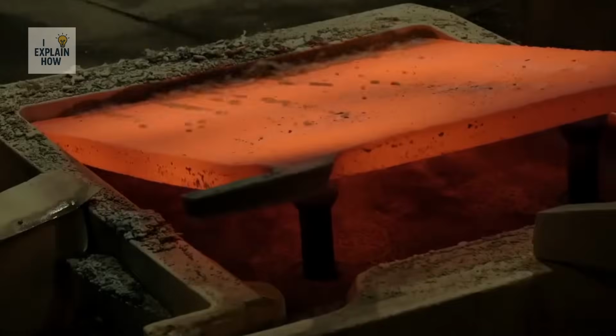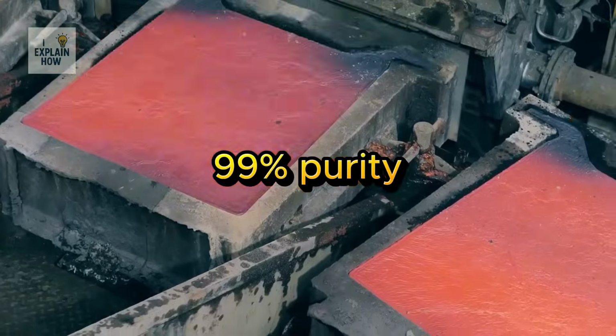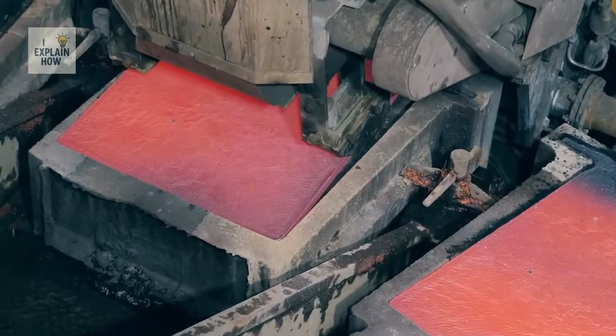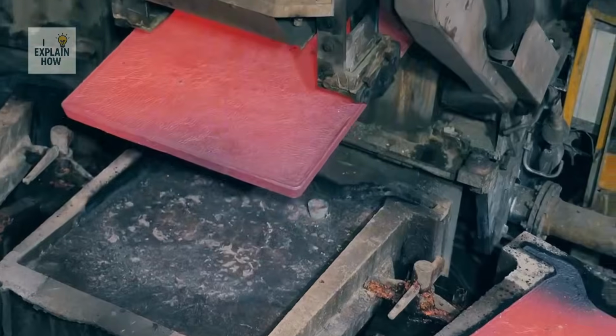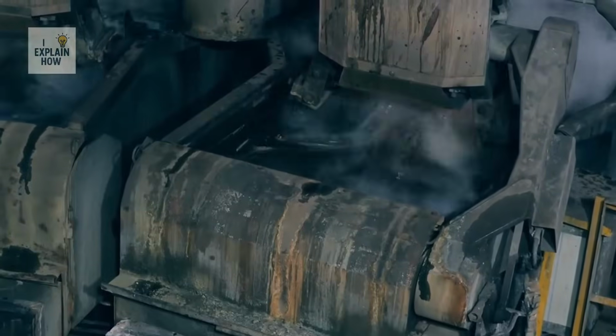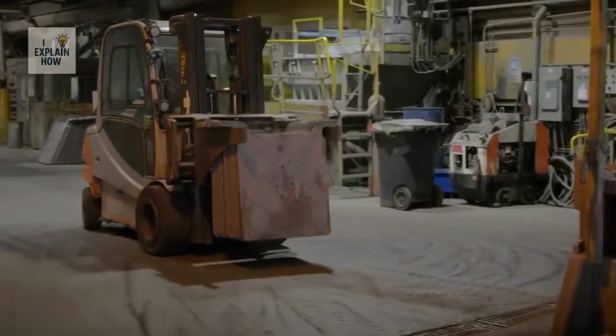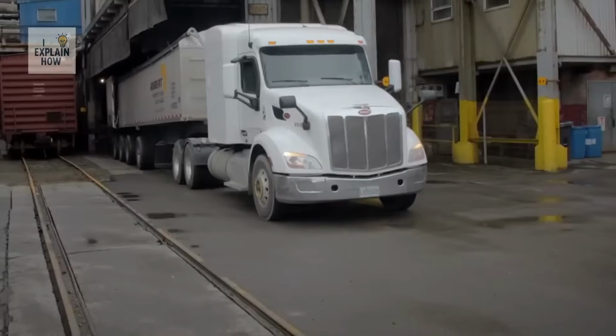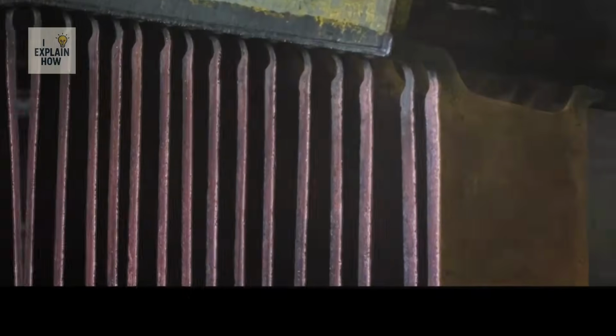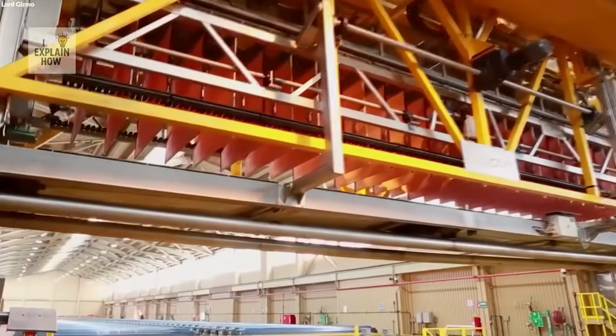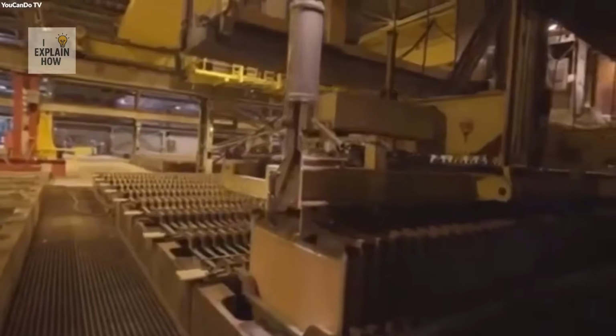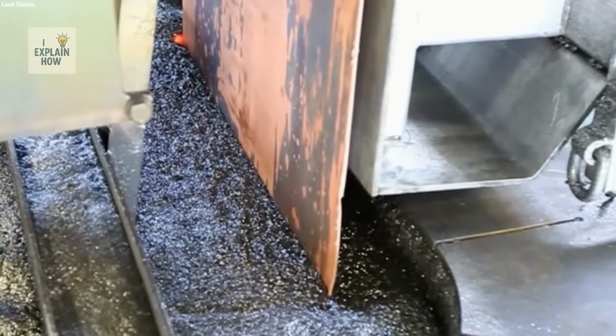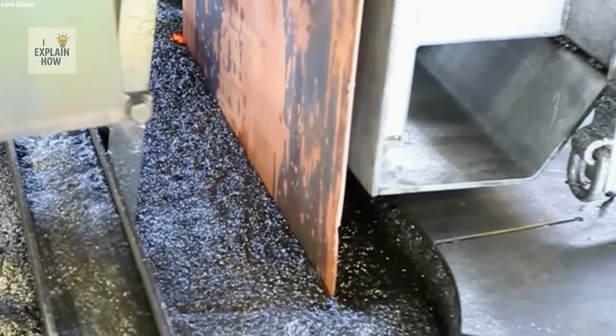The purity then rises to 99%, and the molten copper is poured into large molds to form massive rectangular plates called anodes. These plates are cooled by water jets, solidified, and then ejected by hydraulic cylinders. They are then cleaned to remove mold release agent residue and transported to a refinery, sometimes hundreds of kilometers away.